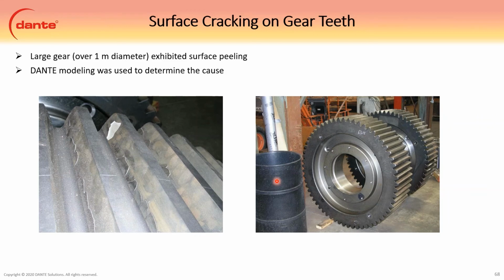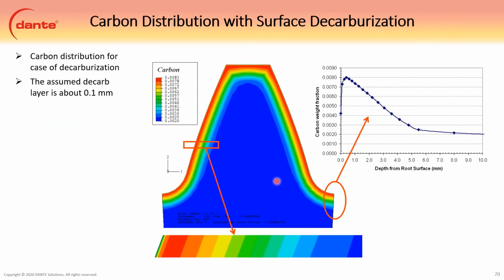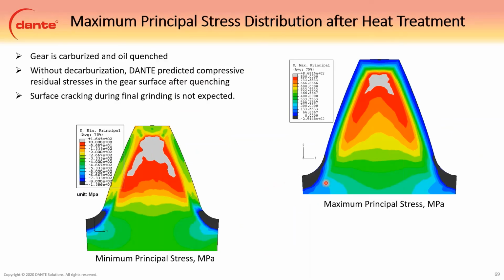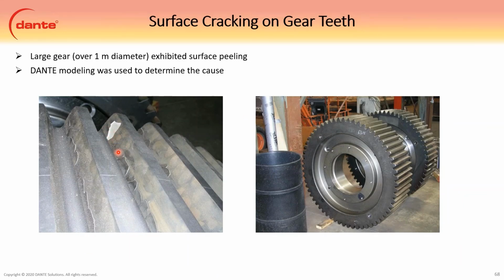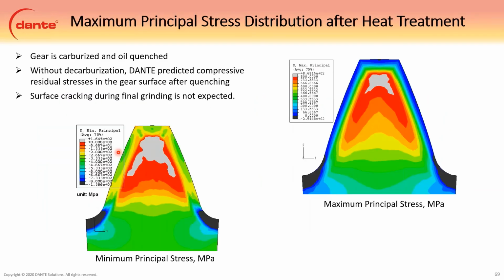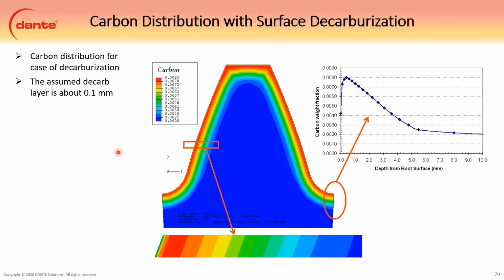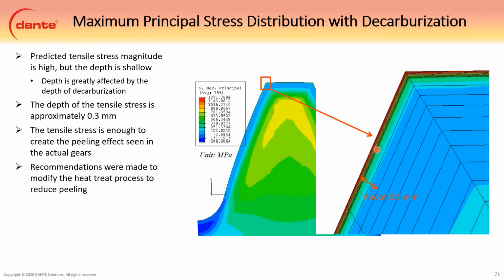Decarburization we can model. So this was peeling of a gear, just looking at decarb. Without decarburization, we predicted a high compressive residual stress, and there was no reason this thing should be cracking. It was cracking during the final grinding process. You can see as they ground it, it would start peeling. So we predicted all should be good and it should not crack. So we looked at what happens if this thing is decarbed 0.1 millimeters. And then we predict a shallow surface tensile stress, which would cause the peeling. This is shallow, probably about 100 microns maybe. So it's not too deep, but it is there. It says the tensile stress goes 300 microns.